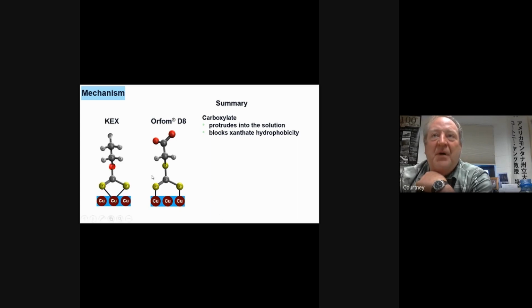And here is a model of the ethyl xanthate adsorbing. In this case, just to show you the difference, this sulfur and this sulfur are bonding to the same copper, and that's a bidentate. Otherwise, they're almost the same length. This is a little bit taller than the xanthate. Everything is the same.